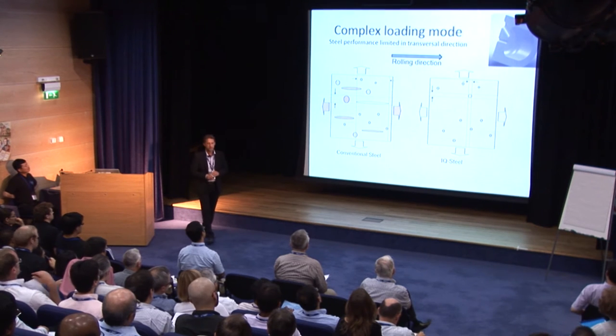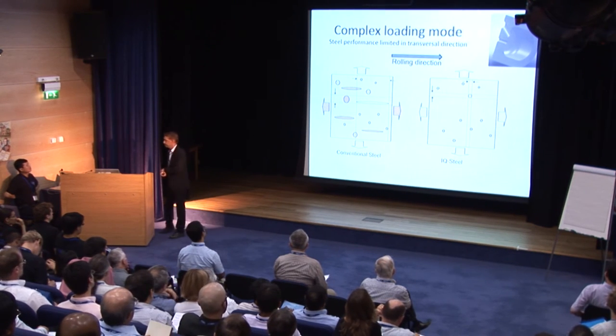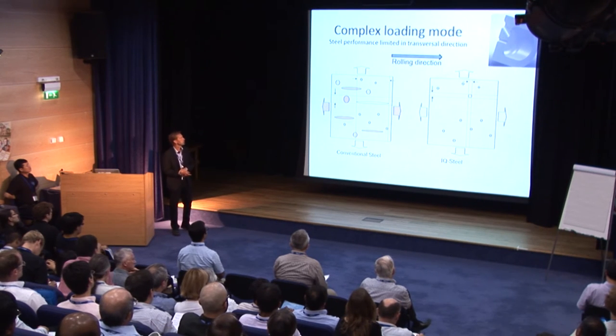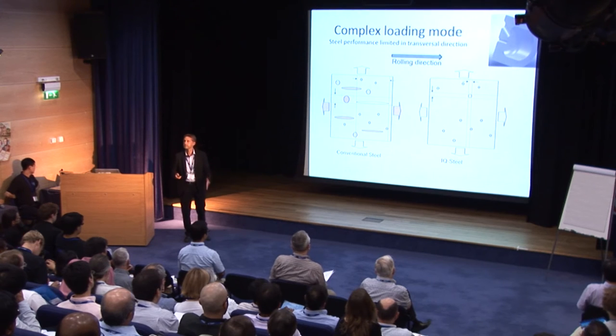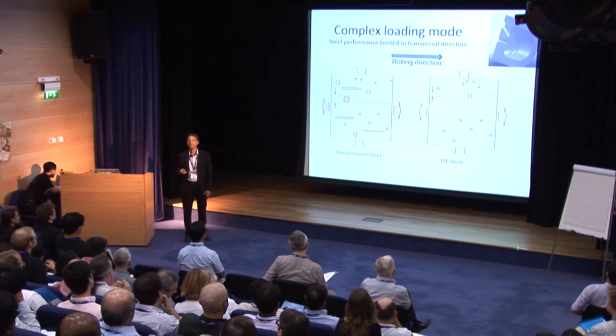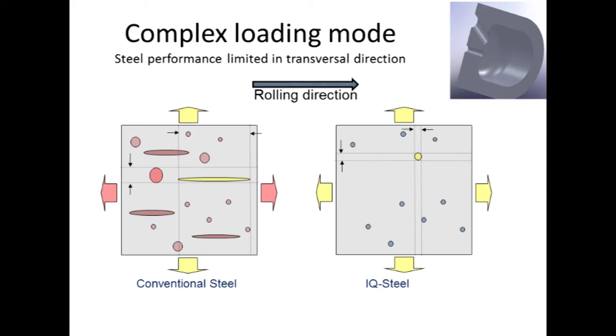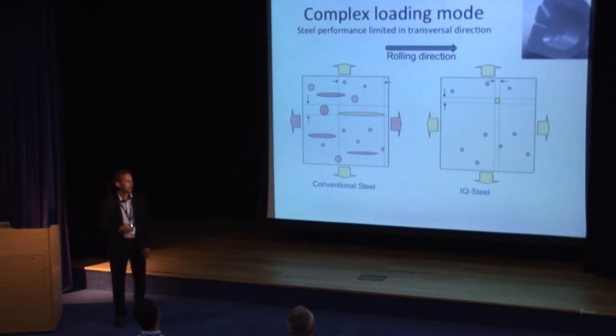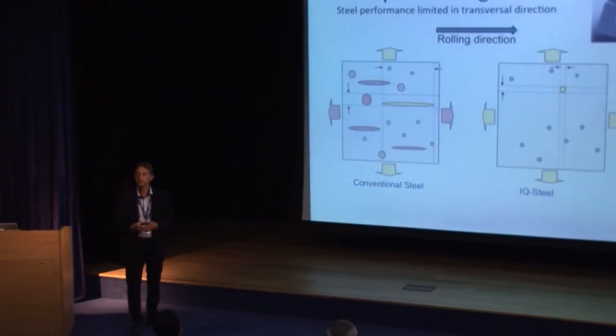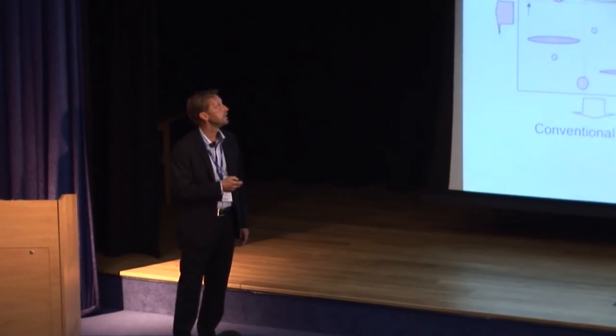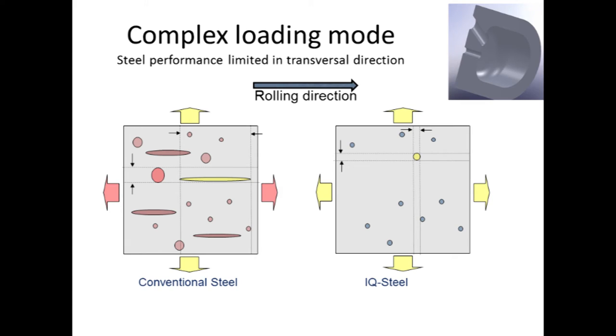Okay, that was the general part. And then going into the isotropic part. What we see today is that more and more products are highly stressed in very many different directions. This is an example of a fuel injection part, where you have a hole drilled there, and a chamber subjected to a pressure of around 2,000 bars, which means that in these kinds of holes, in all directions, you will have very high stress generated. If you have elongated defects in that region, going out from that, they can potentially cause a fatigue failure.